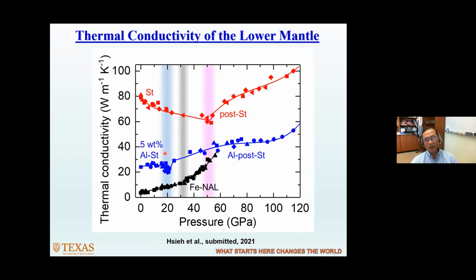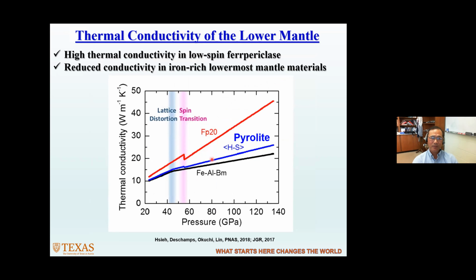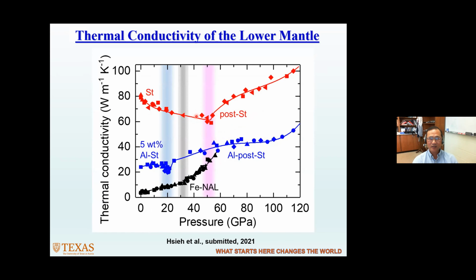And the lower mantle can also have some subducted slab materials that are made of like basalt that undergoes phase transformations. One key mineral in subducted slab materials is stishovite, and another one is the NAL phase, a new aluminum-rich phase in the subducted slabs. Surprisingly, stishovite actually has very high thermal conductivity, as high as almost like 80 watts per meter per Kelvin. We can actually compare that to ferropericlase and bridgmanite, which are somewhere around 10 to 40 watts per meter per Kelvin. So stishovite has very high thermal conductivity.